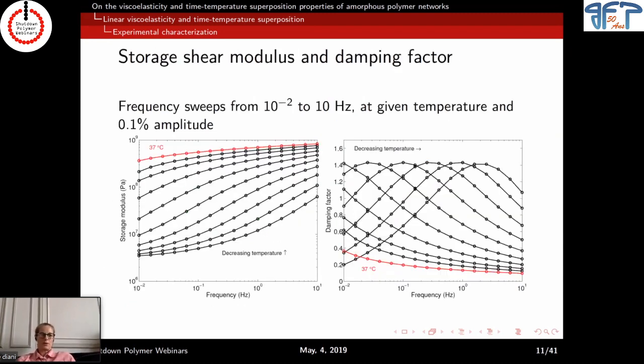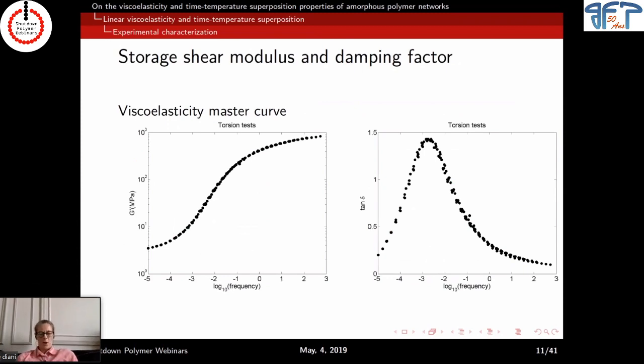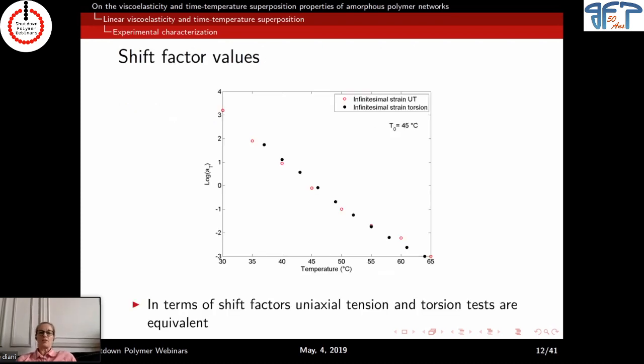Okay, so now that we know that, we're careful. And so we use long, thin samples. And we did the frequency sweeps from 10⁻² to 10 Hertz, still at a given temperature, with small amplitude of strain. And we build the master curve for G prime and tangent delta, as we did for E prime and tangent delta. So the first thing, if we look at the shift factor for both tests, we can see, building the master curve at the same reference temperature, we have equivalent